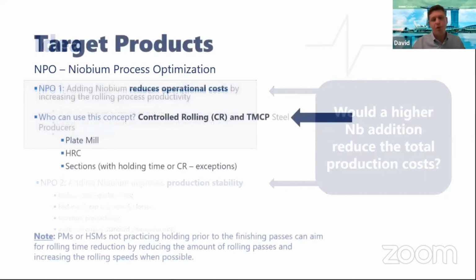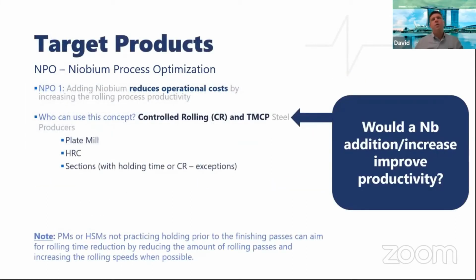And it's important to mention that this concept is not meant for conventional rolling. This is meant for controlled rolling and TMCP steels, which currently already use niobium or which do not use any microalloy, but target a reduced finished rolling temperature for toughness purpose, for example.